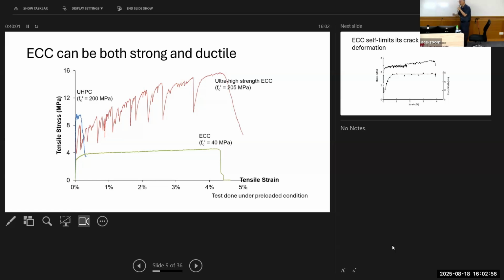If necessary, and Professor Dai's group, I believe, has also produced this kind of high strength ECC. ECC with high ductility, that's typical of all ECC. That's the common factor for all members in the ECC family, but you can actually also get high compressive strength as well. I just came back from Shanghai. The group I was visiting is at Tongji University. They have also produced very high compressive strength ECC. Actually, they used it in a 2-story building and tested it on a shake table, and it works beautifully. The most amazing thing is there is no steel reinforcement inside. It's 0 steel reinforcement. It's totally dependent on the ECC.